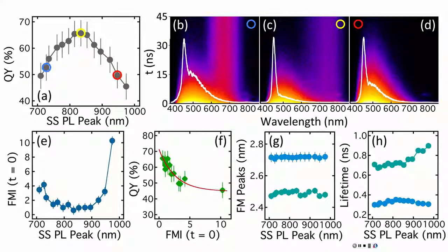It's not just the single lowest energy level, right? That was my understanding. The splitting in energy is affected, right? So wherever you go, high energy, low energy, they all should be affected. Pretty much the same as in carbon nanotubes: E11, E22, E33, they all feel the change in the diameter of the nanotube, not only E11.